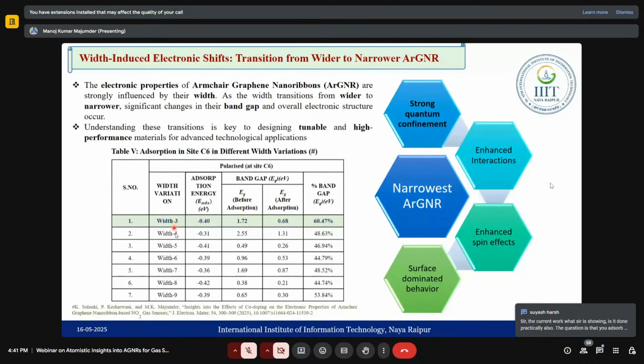And we can see here in this table we are using different widths of the AGNR, like width 3 to width 9. Okay, so if we go for the narrower or the narrowest, that is width 3, the absorption energy will be more, and the percentage band gap is also 60.47 percent. If we compare the band gap before absorption and after absorption, the percentage difference is 60.47 percent, and that is a very good thing for our device application, that is the sensor applications, correct? So that's why if we use the narrowest or the narrower kind of AGNR channel, it will always be better for the application.